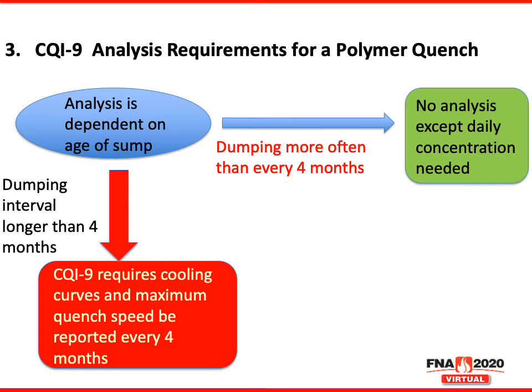However, if your dump cycle is longer than 4 months, you're producing automotive parts that are CQI-9 registered, you have to have cooling curves at a minimum of every 4 months, and the maximum quench speed must be reported. You can't get the maximum quench speed without a cooling curve. So again, if you're more than 4 months old for your sump, send in a sample to your supplier and let them run it.